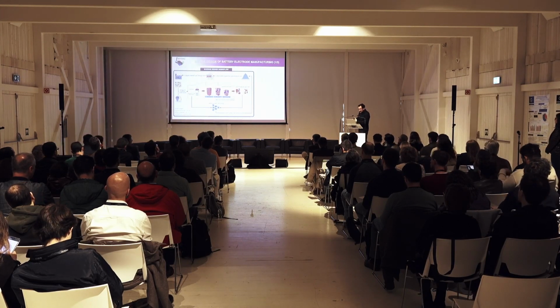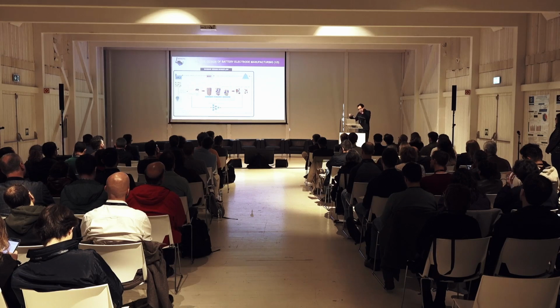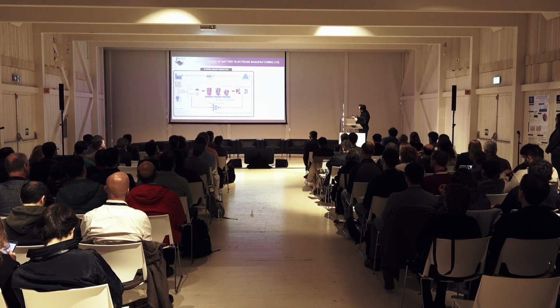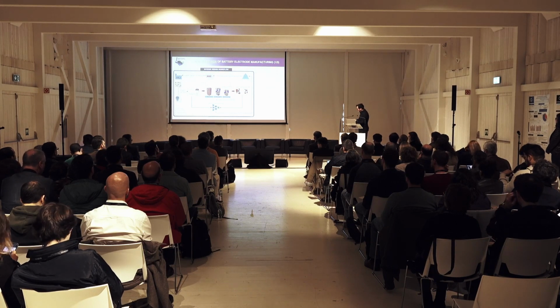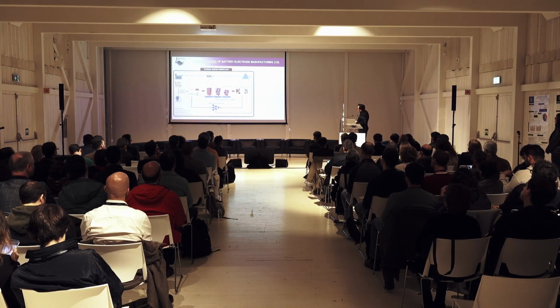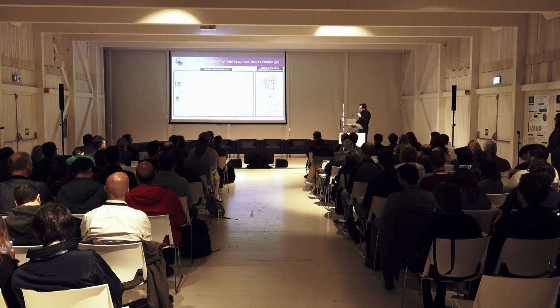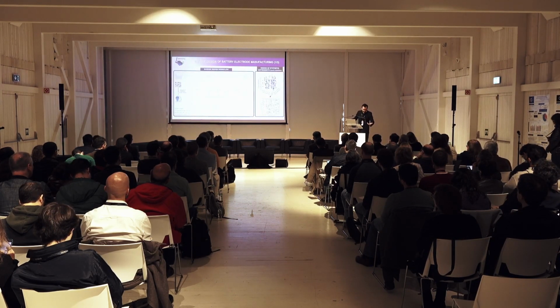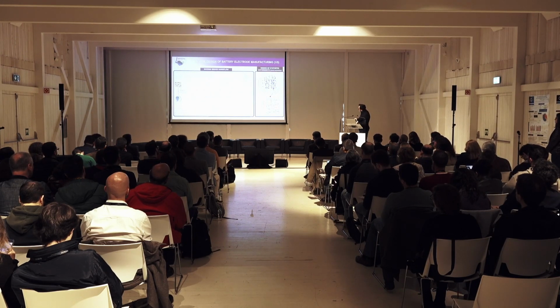And then we derive this machine learning model, which is now high speed. In a few seconds it gives you responses, right? I apply these manufacturing parameters, then I get these electrode properties. We embed this high-speed model now in a Bayesian optimizer to predict which manufacturing parameters we need to adopt to maximize or minimize thickness, porosity, and so on and so forth. Here you see a little bit the space of parameters that we have explored, how it looks like. So we apply here Sobol sequences. It's a way of designing your virtual experiments. So we use these different synthetic conditions to run our manufacturing simulator, produce the synthetic data, and then train